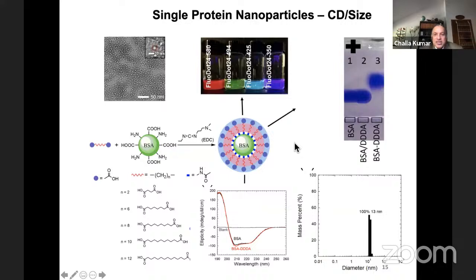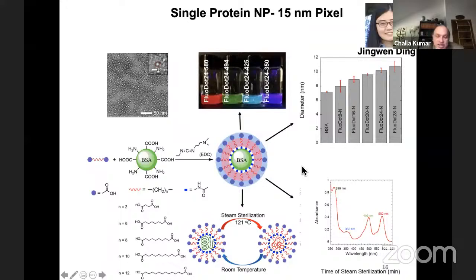And so one of the things that we are concerned about, as I mentioned before, with Jingwen, is that these should be stable. If they're not stable, nobody's going to use them. You can't store it at minus 80 degrees centigrade. So what Jingwen did was to take this and steam sterilize it. Steam sterilization is done by heating at 120 degrees and high pressure. It kills bacteria, kills viruses, and destroys most biomolecules maybe. It's like a pressure cooker. You just put it in a pressure cooker.